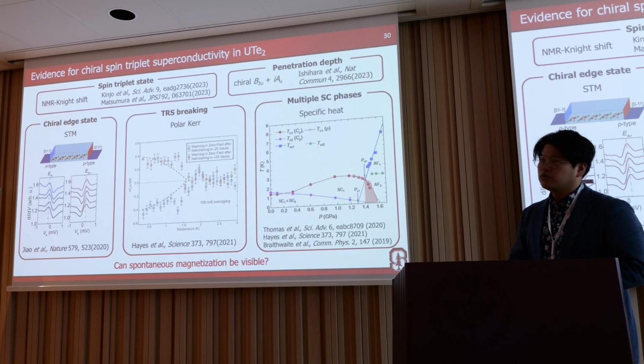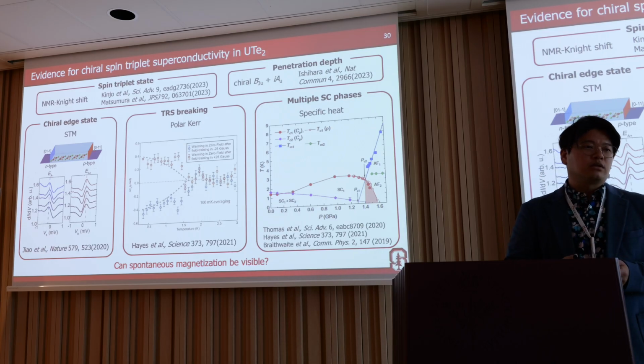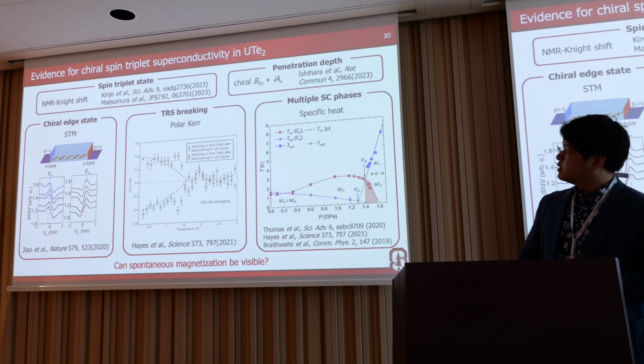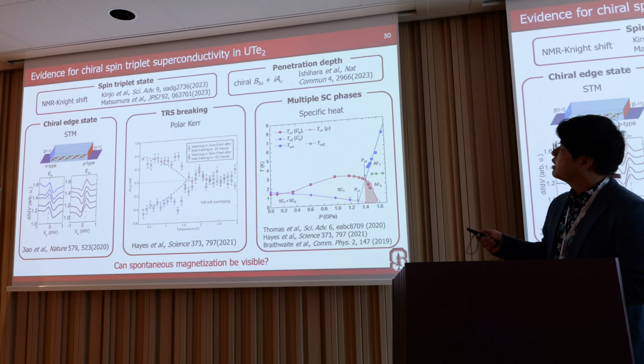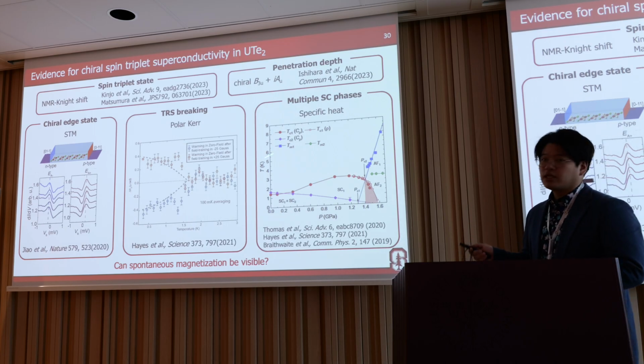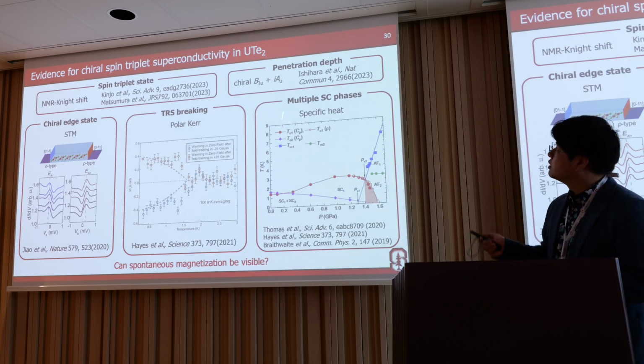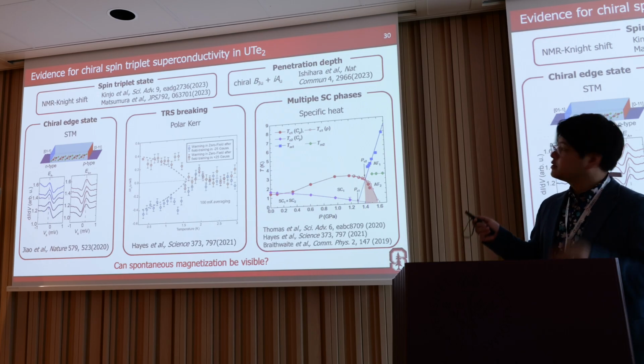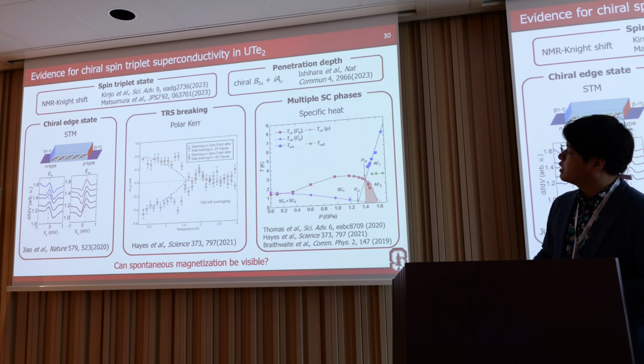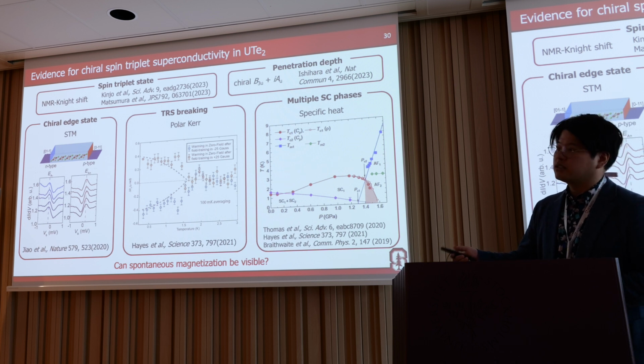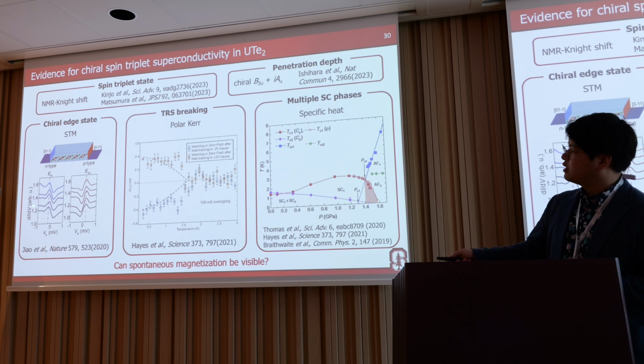And now we have a new candidate chiral superconductor, UTe2. A spin-triplet state is suggested by many Knight shift measurements. There are several types of measurements suggesting chiral superconductivity, such as the chiral state observed in the STM. This is not the chiral current, this is the edge state, so an asymmetric signal.